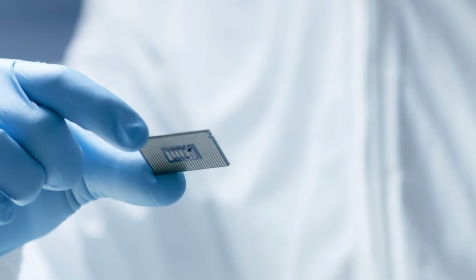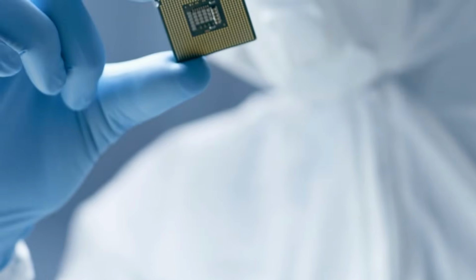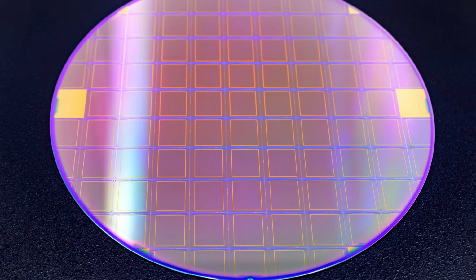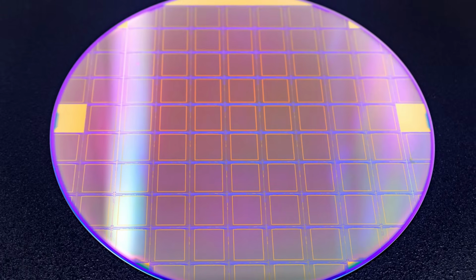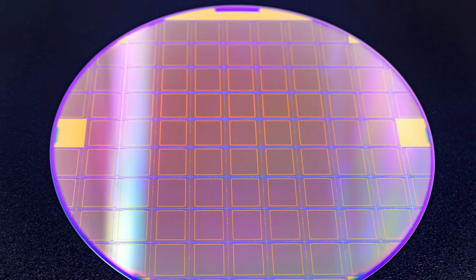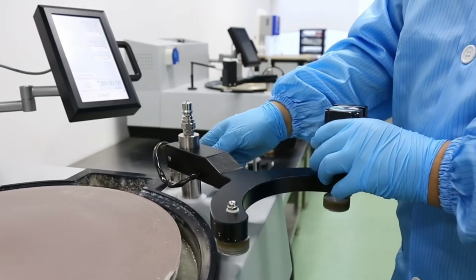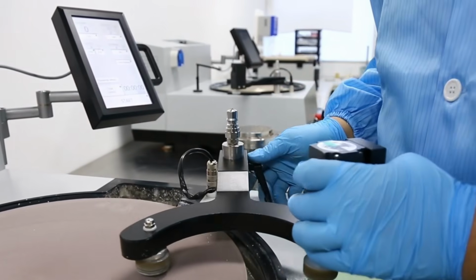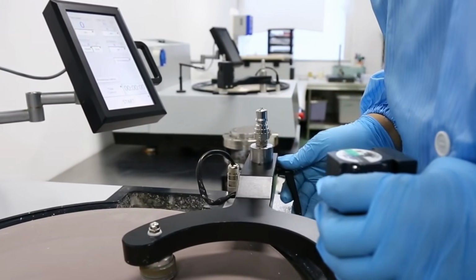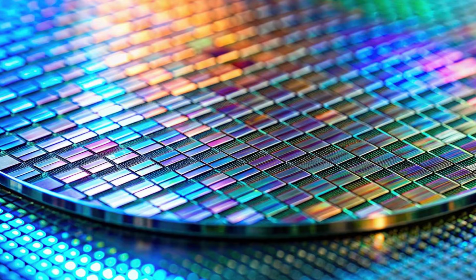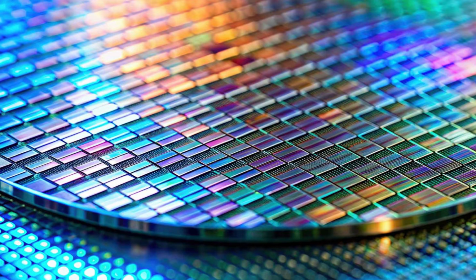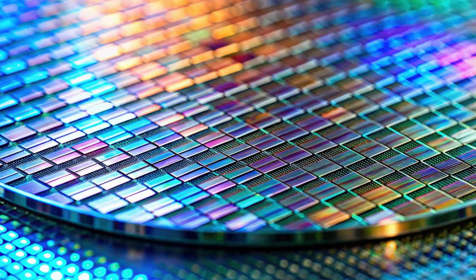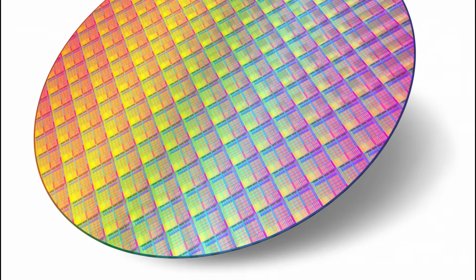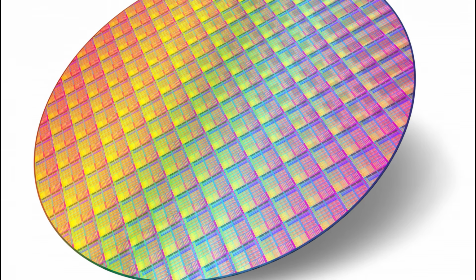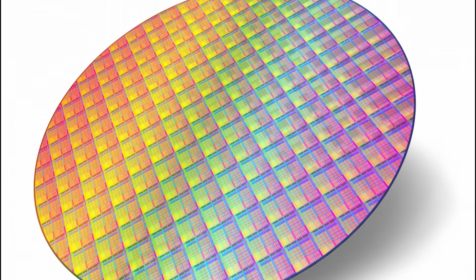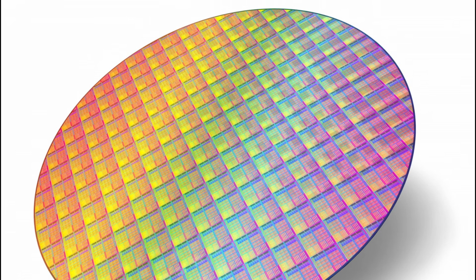And for semiconductors, rough is unacceptable. The wafers are lapped, chemically etched, and then polished in a process called chemical-mechanical planarization, a combination of corrosive slurry and precision pressure that smooths the surface down to the atomic scale. The finished wafer is flatter, relative to its size, than almost any object humans have ever made. If a 300mm wafer were scaled up to the size of the United States, the tallest bump on its surface would stand just a few inches high.